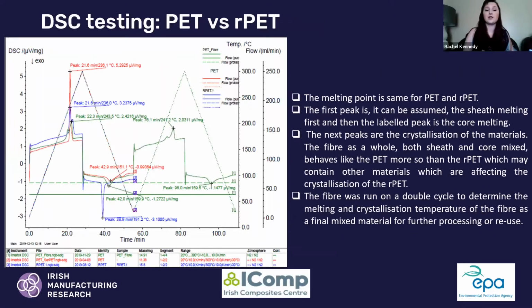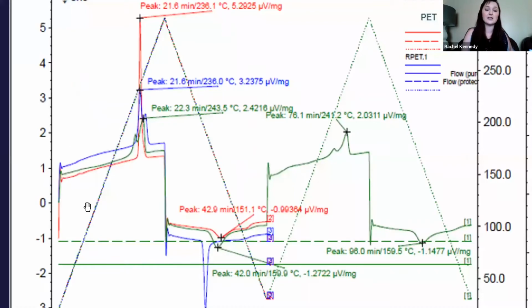To go along with the rheology testing, we also have to do DSC, which is differential scanning calorimetry. What we use this for is to determine the temperature at which your material changes phase. On this graph, we actually have 3 lines. The blue line is the recycled PET, the red is the normal PET, and the green is the bicomponent fiber. The green line is a little bit longer because we actually did a double cycle on this, which I'll explain after.